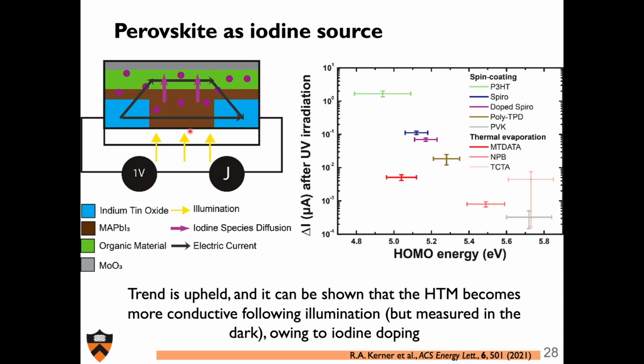If I irradiate the perovskite and then shut off the irradiation, I can measure the transport of the organic, which in the absence of light is way more conductive than the perovskite. The perovskite is very photoconductive, but in the dark, it's very insulating. So I can look at the transport in the organic, and I can see the same trend. Iodine is leached out from irradiation photolysis of the perovskite, and I can see this change in conductivity in that organic hole transport layer.